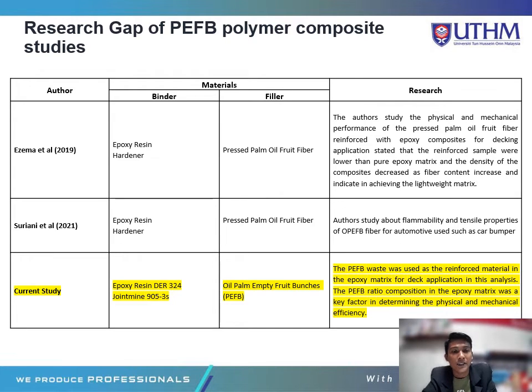Ezema 2019 used epoxy resin hardener as a binder and pressed palm oil fruit fiber as the filler to study the physical and mechanical performance of pressed palm oil fruit fiber reinforced epoxy composite for decking application. It stated that the reinforced samples were lower than the pure epoxy matrix, and the density of the composite decreased as fiber content increased, indicating a lightweight matrix. And Suriani 2021 used epoxy resin and also pressed palm oil fruit fiber to study the flammability and tensile properties of PEFB fiber for automotive use such as a car bumper.